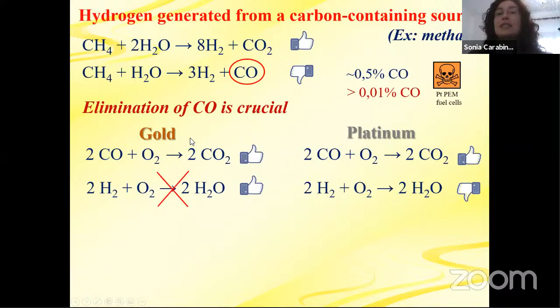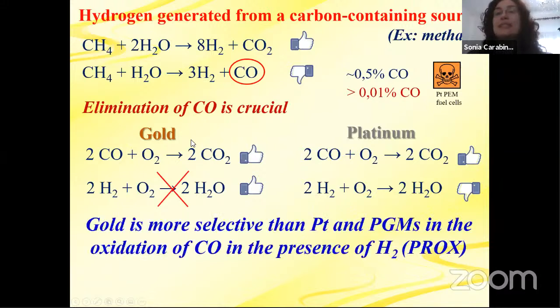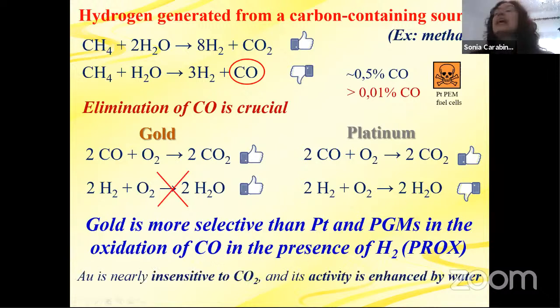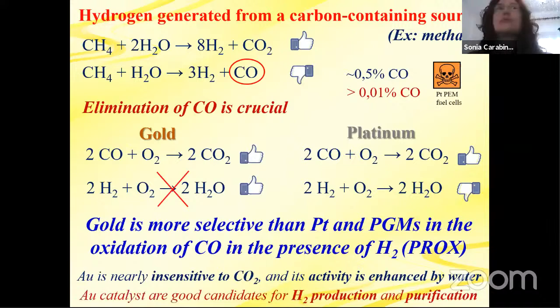It's much more selective than platinum and other platinum group metals for the oxidation of CO in the presence of hydrogen, which is the so-called PROX, or preferential oxidation. So gold prefers to oxidize CO, it doesn't oxidize hydrogen. So that is quite good. And gold also is nearly insensitive to CO2, and its activity is enhanced by water. So gold catalysts are very good candidates for hydrogen production and purification in these needs.